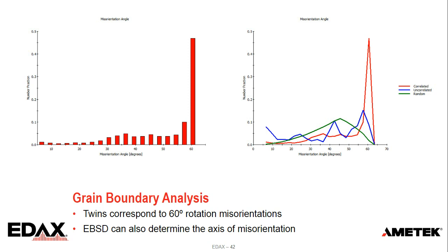The twin boundaries, the primary twins, are 60 degrees about a 1-1-1 axis. We can also do some analysis there on the right, where we look at what we call the correlated misorientations. That's looking at the misorientations point to point. We can look at the uncorrelated, where we compare one point to every other point. And then we can look at what a random distribution would look like. This gives us an idea of how the spatial distribution of those orientations influences the grain boundary character distribution.